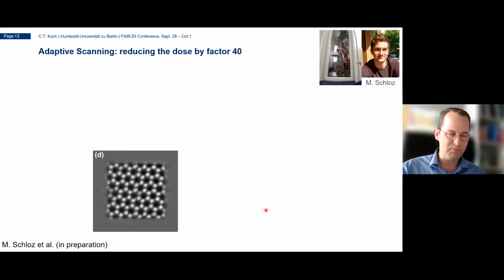So this is just an example to show you that having these data-aware algorithms or data-trained algorithms, you can now even feed back into the experiment and drive the experiment based on the data that you have already collected prior. So this is one of these ptychography reconstructions obtained in our microscope here in Berlin. And this is a very simple material. It's a monolayer of molybdenum disulfide. And so many diffraction patterns have been collected, and then the reconstruction algorithm has run and produced this beautiful reconstruction